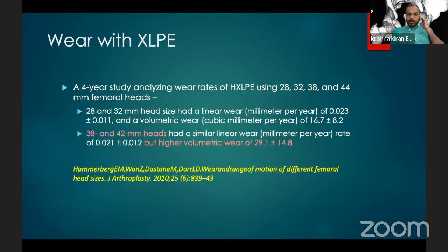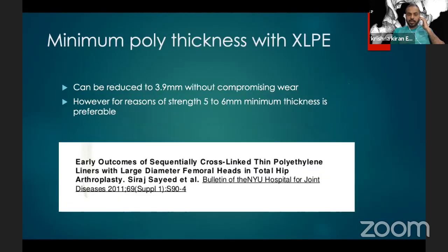Now, the most important are the studies. The wear with XLPE has been shown, across all head sizes, to have a reduction in linear and volumetric wear. You can reduce the minimum thickness of polyethylene to 3.9 millimeter without compromising wear. For reasons of strength, however, we must choose a poly which is between 5 to 6 millimeter minimum thickness in order to avoid a fatigue type of fracture.